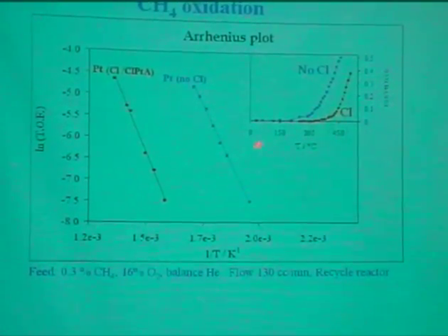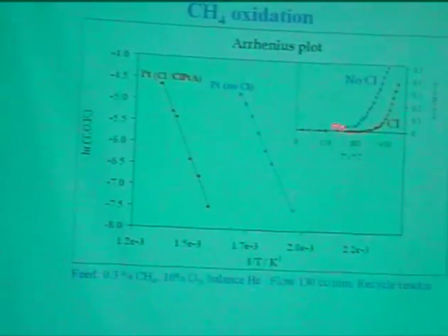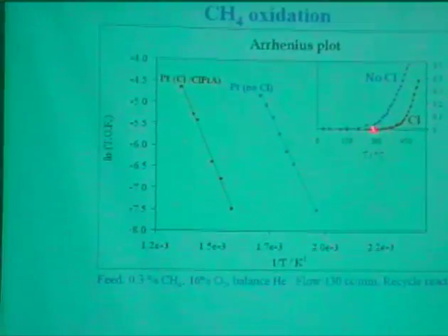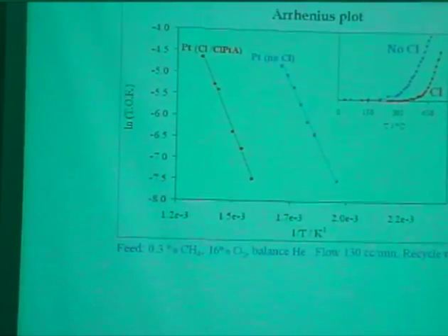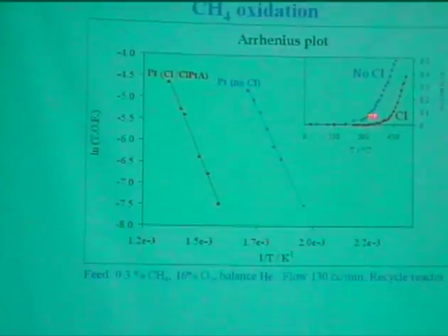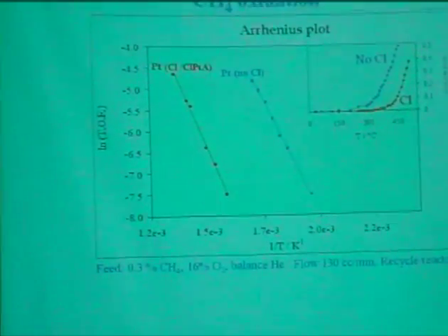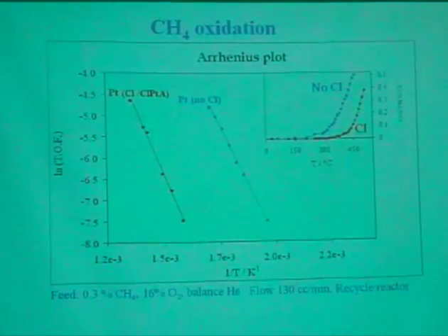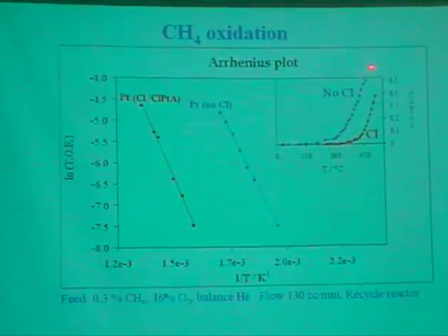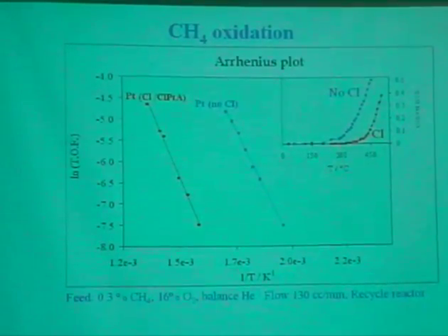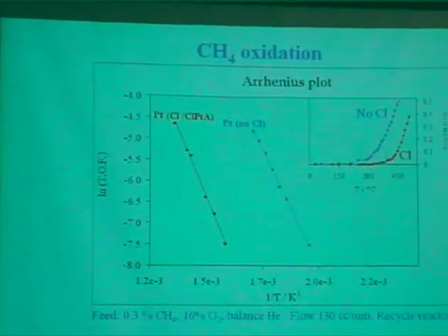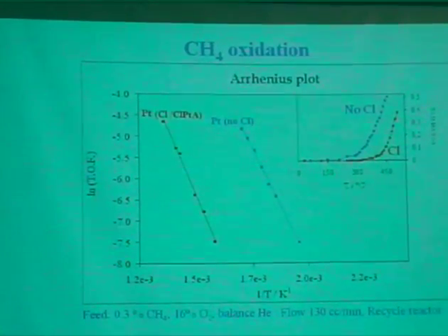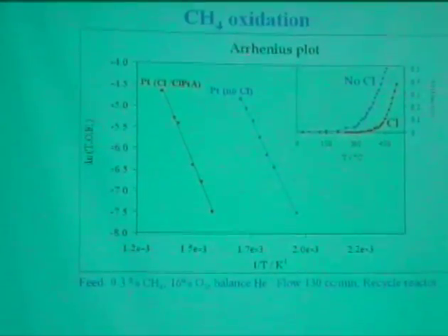So this is a typical profile of conversion versus temperature. If you don't do this in a recycle reactor, what normally happens is the conversion jumps to the high steady state at one point all by itself. Here you can really measure up to 50 percent or higher conversions if you want. We try to stay below 450 to prevent any sintering complicating the results.